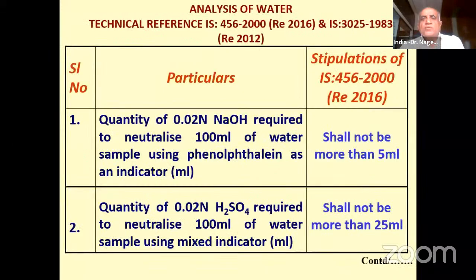Now, let us come to the specification part. The specification given in IS 456, when tested as per IS 3025. So these particulars, whether it is an alkalinity test or acidity test. First one is an acidity test. A quantity of 0.02 normal NaOH required to neutralize 100 ml of water sample using phenolphthalein as an indicator shall not be more than 5 ml.